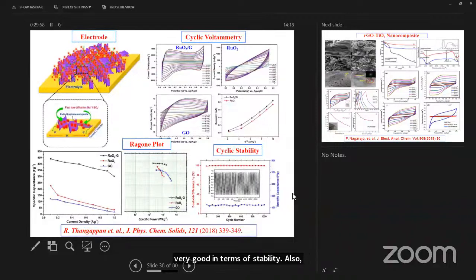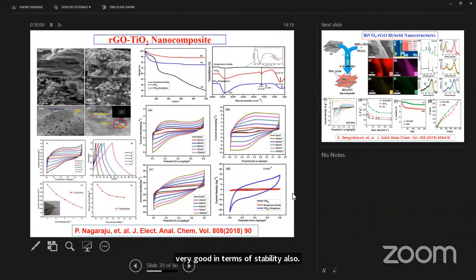Okay. So having done this, we also tried with different metal oxides like titanium oxide, and with this titanium oxide we fabricated a 2 electrode supercapacitor cell and then studied the performance. Here you can just see the current densities of the order of ampere range, which is also good for electrodes.